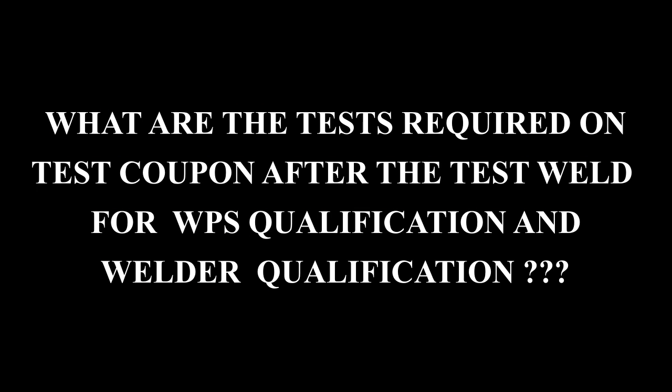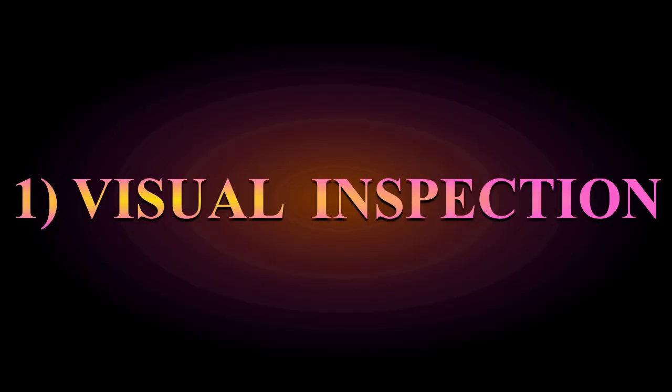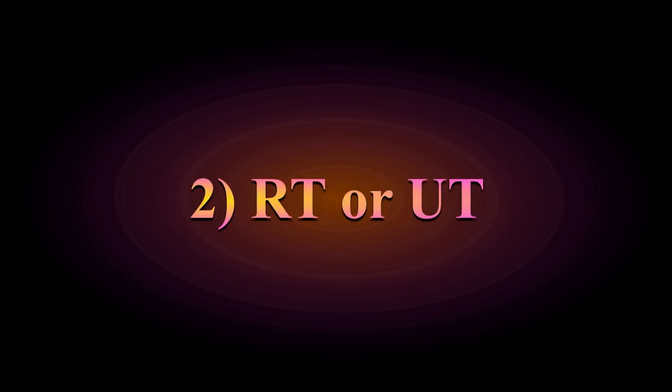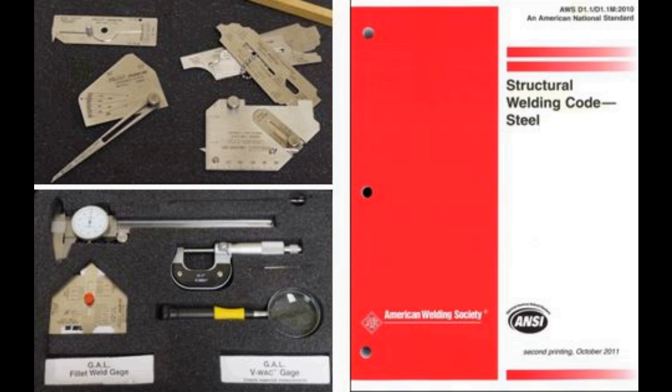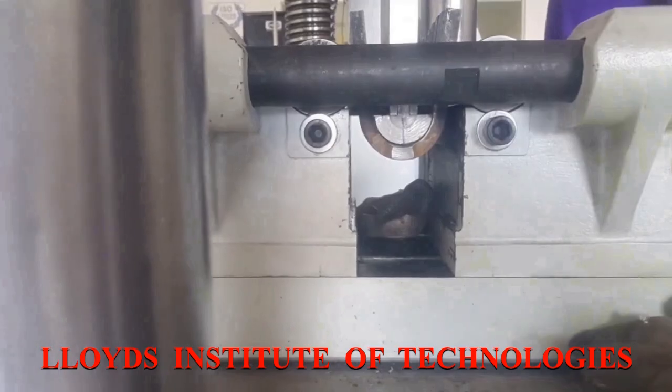For the WPS qualification, you have to go for various kinds of tests: destructive tests, non-destructive tests, and of course visual inspection initially. That means after completion of the test weld by the welder, the first thing to be done is the visual inspection. According to AWS D1.1, all the visual inspection parameters are considered, and if found okay, then you move on to the next NDT test, that is either a radiographic test or an ultrasonic test. After successful completion of both the visual inspection as well as the radiographic or ultrasonic test, only then can you go for the mechanical test.